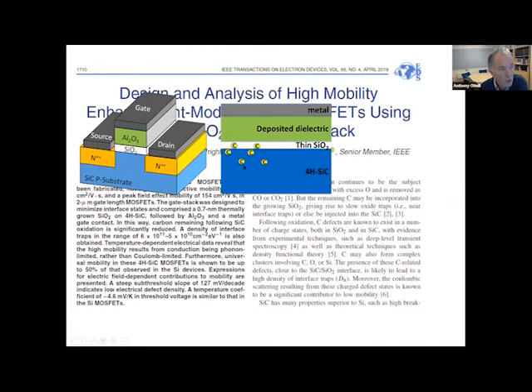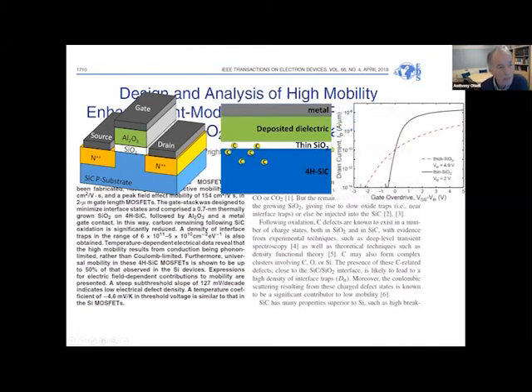Because it's a thin oxide, you don't get as many defects. And when you look at the IV characteristics, the solid black line, this is a plot of drain current vertically and gate voltage horizontally. You can see you're getting a really good IV characteristic with the thin oxide approach compared with the control thick oxide approach. So for example, the subthreshold slope, although it's not 60, it's about 120, which is still pretty good compared with about 500 as a subthreshold slope, millivolts per decade, for the thick oxide approach.